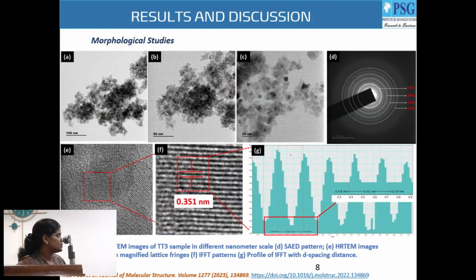So we enlarged the predominant peak of 101, and there we can see a slight shift in the XRD of the dopant TiO2. Thus we come to know that tantalum is present in the TiO2 lattice. I am also showing the FTIR of the tantalum-doped 3 weight percentage and TiO2, at 987 inverse centimeters. It shows the tantalum bonding with TiO2, which confirms the presence of tantalum in TiO2.